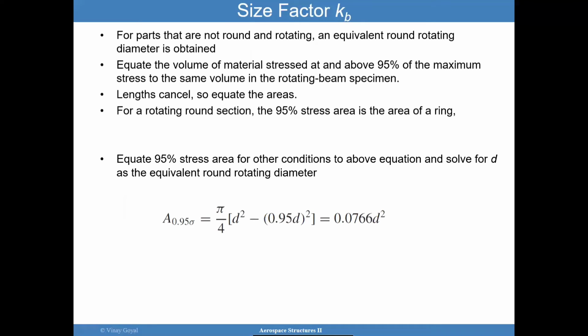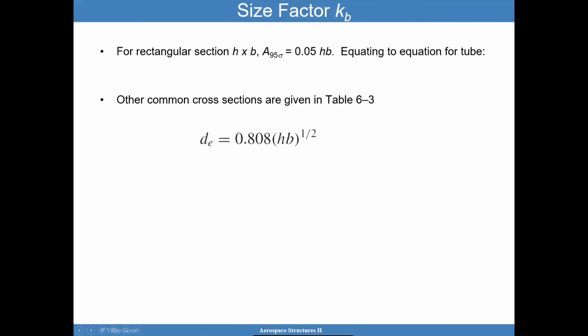For parts that are not round and rotating, an equivalent round rotating diameter has to be obtained. One way to do that is to equate the volume of the material stressed above 95% of the maximum stress to the same volume in the rotating beam specimen. So the lengths will cancel, but you want to equate the areas. So for a rotating round section, the 95% area is the area of the ring. And so you have to calculate the area of the ring and then come up with an equivalent value of D for a rotating diameter. And that's given here as an example. That's for the ring and that's for a rotating diameter. And then you solve for D.